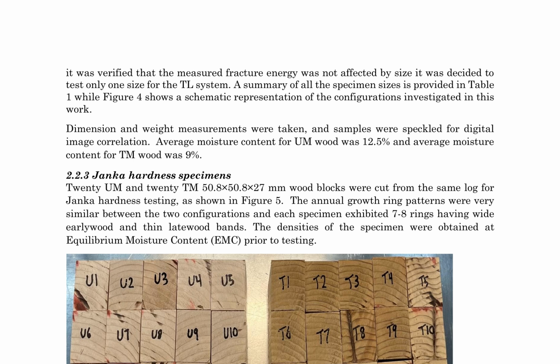For Janka hardness testing, 20 specimens each of untreated and TM wood were prepared from the same log, with dimensions of 50.8 x 50.8 x 27 mm. Figure 5 displays the specimens, illustrating similar annual growth ring patterns and exhibiting 7-8 rings with distinct earlywood and latewood bands. Prior to testing, the densities of the specimens were obtained at equilibrium moisture content, EMC, with average moisture content values of 12.5% for untreated wood and 9% for TM wood.